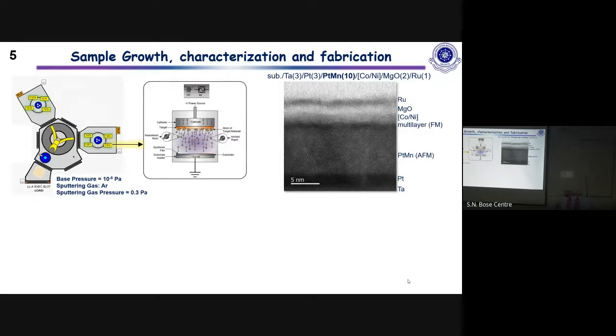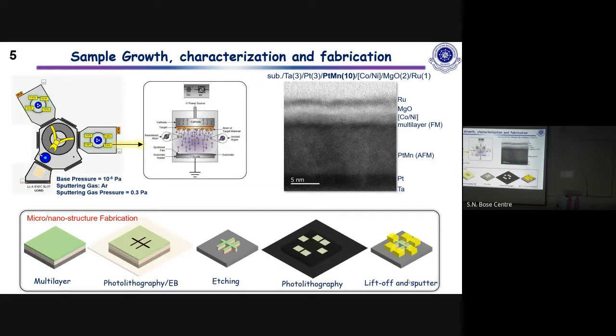This is a polycrystalline sample which is grown on silicon and which has several different layers of tantalum, platinum, manganese, ferromagnet, and cap. What we actually do is we first grow these samples by sputtering, and then we use photolithography. Most of the time we use photolithography, and for some experiments we also use electron beam. We then use argon ion etching or argon ion milling techniques to fabricate devices, and then we measure the transport under the magnetic field or the radiation. So this is basically the workflow that we generally have.